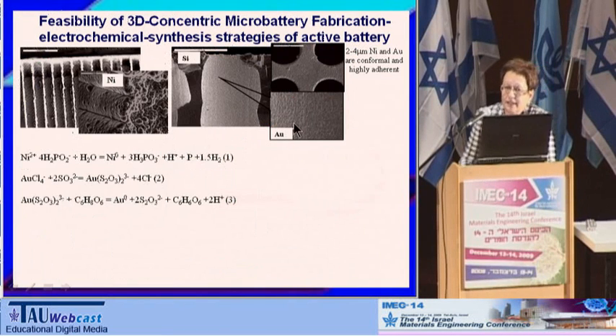This slide summarizes the technological process as a whole, and I would like to emphasize at this point that this thin-film three-dimensional concentric microbattery, which was fabricated both on perforated silicon and glass capillary array plates, was fabricated using solely wet chemistry and electrochemistry methods. From these planar and cross-sectional SEM images, you can see that the thin layers of nickel current collector or gold current collector are continuous and coat all the available surfaces of the substrate.